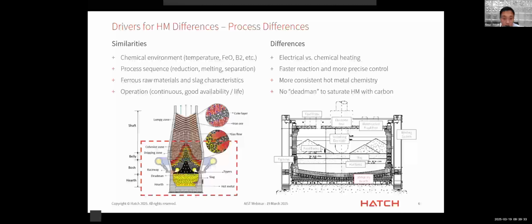Again, as we've understood, there is no such thing as a dead man inside the ESF, that giant mass of carbon, whether it's floating or sinking, that carburizes the hot metal to saturation level. That does not exist inside the ESF, and therefore, as the previous presentation mentioned, the hot metal is not expected to be fully carburized to this level of saturation.